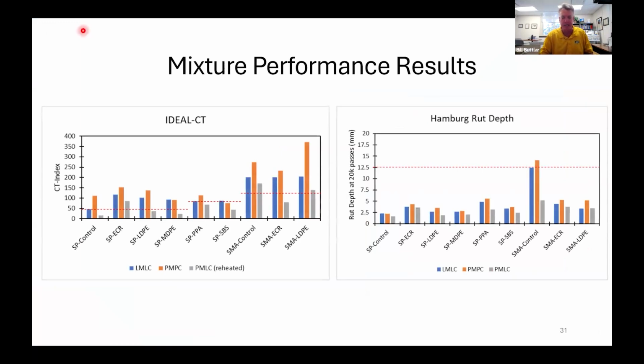As far as cracking and rutting scores, cracking on the left, rutting on the right, we did both the design, which are the blue bars, lab mixed, lab compacted; the non-reheats, which were plant mixed, sampling right out of the trucks, keeping it hot, putting it right into the gyratory, plant mixed, plant compacted; and then the reheats, because sometimes those are used for QA. And so we want to see where those numbers are going. Usually it gets more brittle in the CT, and you might get a little more stiffness bump in the Hamburg with the reheats. You get quite a bit. So you can see how those numbers look.